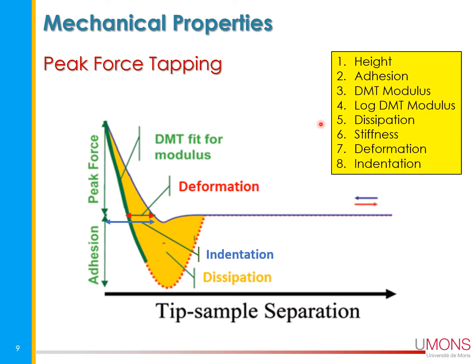So we have this force curve, and in real time, it's possible to calculate, for instance, here, the rigidity modulus by the DMT as we saw before. We can measure and estimate the dissipation, the indentation, and the deformation. So when you are performing peak force tapping, what you have is actually 8 pieces of information corresponding to what you have measured. You have the height, the adhesion, the modulus, the log modulus, the dissipation, the stiffness, the deformation, and the indentation.